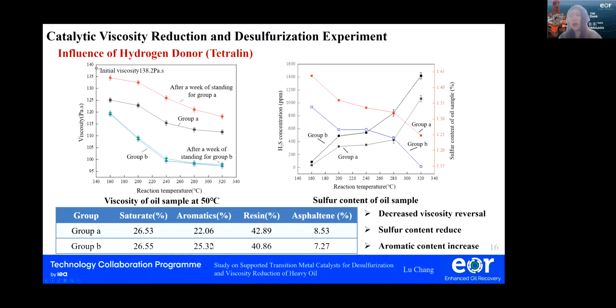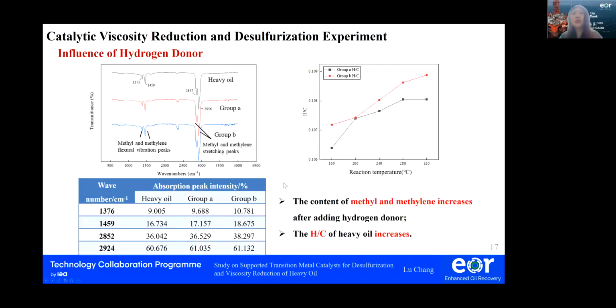And the SARA table shows that the aromatic contents increased, which proves that the addition of hydrogen donors promotes the hydrothermal cracking reaction and helps the upgrading of heavy oil. And we also did the FTIR test, and the spectrum of heavy oil group A and group B oil samples are shown in the left-hand side graph. And there are 4 main absorption peaks in the oil sample, which represent the absorption vibration peak and the stretching vibration peak of the methyl group and the methylene group, respectively.